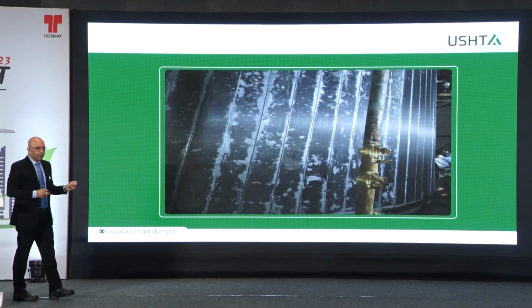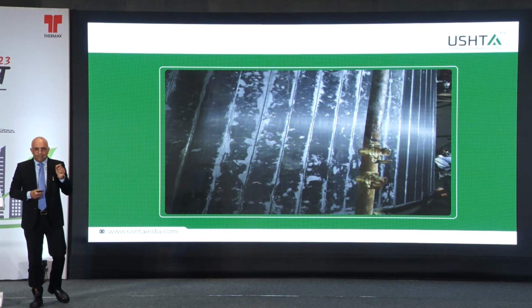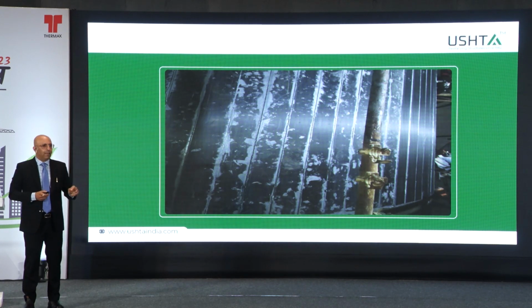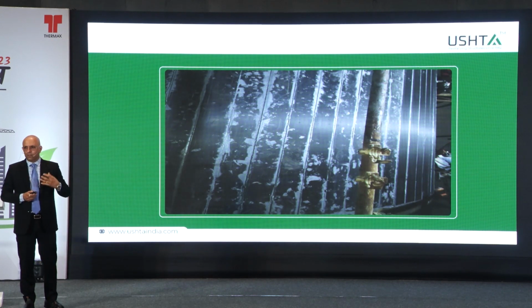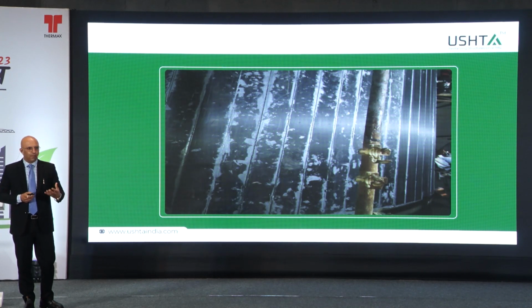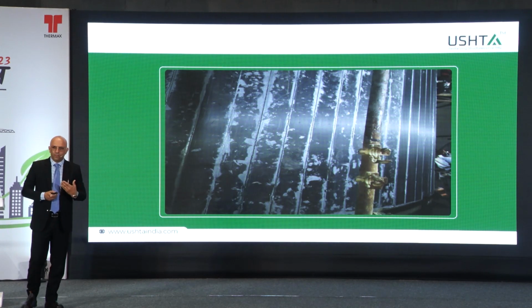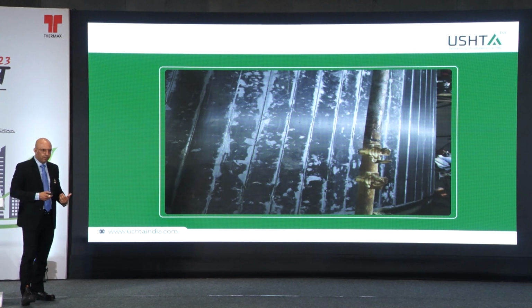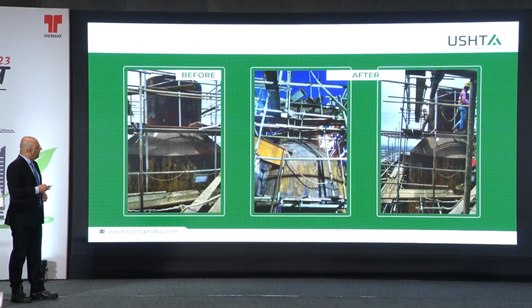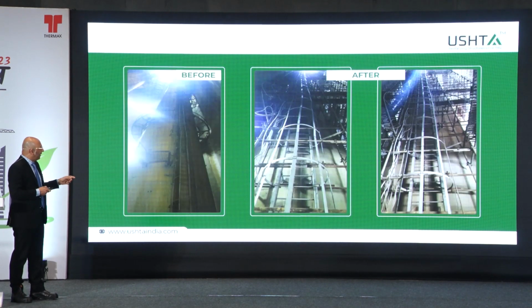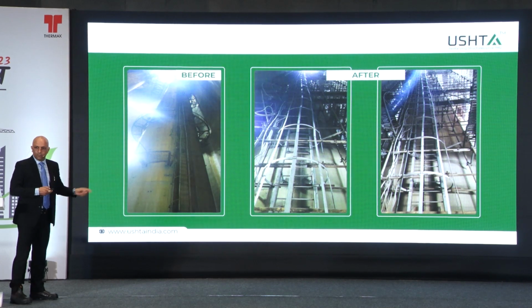So these are laminates which we have used, and the resin which is here is a vinyl ester resin, because sulfuric acid would not, epoxy and other material would not work here. So we resorted to using vinyl ester resin here. And the staircase was replaced by SS304.